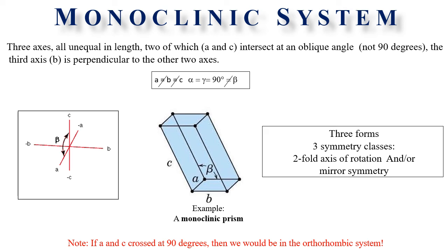In a monoclinic crystal, in the reading position, when the clinoaxis runs up and away from the observer, the orthoaxis runs right to left, and the vertical axis C is in fact vertical. The obtuse angle between the clinoaxis and vertical axis is of importance and is of course fixed for each mineral species.